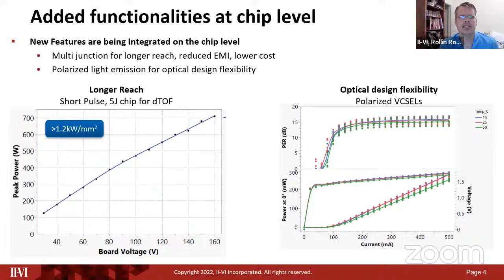So I think that's important. I think the other thing too with the multi-junction, with the 5-junction and up to 8 junctions in some cases, if you run at these really short pulse widths, 5 nanosecond pulse widths, at very low duty cycle, at something like 0.1% duty cycles, you can really push these devices to very high peak currents or peak powers for some of these longer range LiDAR applications.